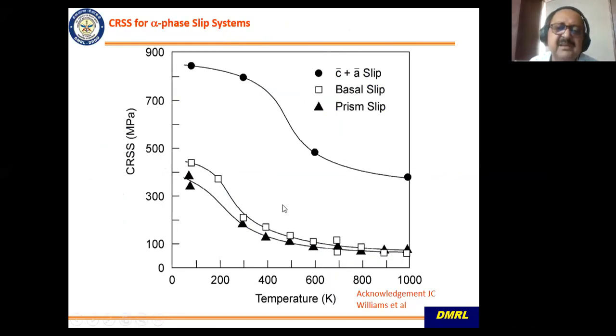The main reason is if you see the critical resolved shear stress, this is plotted for Ti-6Al single crystal, which is the alpha phase, which is there in most of the high temperature titanium alloys. This is the prismatic slip CRSS, and then this is for basal slip, and almost through the temperature range they are similar, although prismatic is lower as compared to basal slip because of the c/a ratio. And when you have c+a deformation, this is almost twice or thrice of this CRSS requirement. So deformation to cause c+a slip is very, very difficult. It requires a higher stress level.